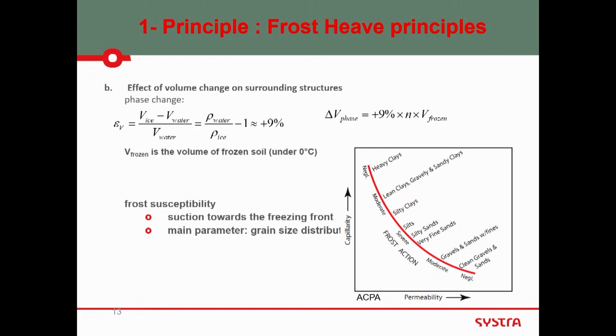When the soil is gravel, when it's high permeability, big grains, in fact, capillarity tends to zero because the size of the equivalent pipe is very large. You see, for example, if you take a glass of water, kind of long, you never see the water going up. Capillarity goes to zero because the contact is very small relative to the volume of water. If your contact is large compared to the volume of water, capillarity develops and water goes up naturally because of this contact force. So the rougher the material, like gravel, the less capillarity you get. So you see where there is sand, gravel, you don't have the water coming to the front.